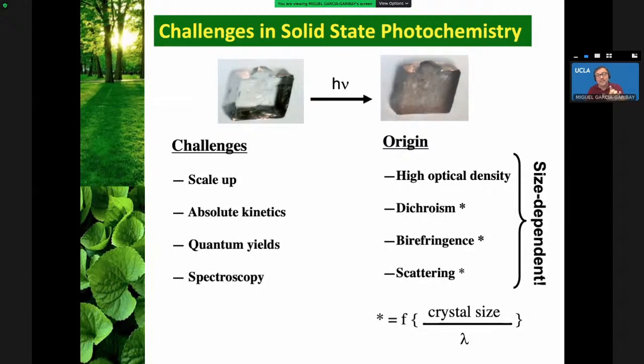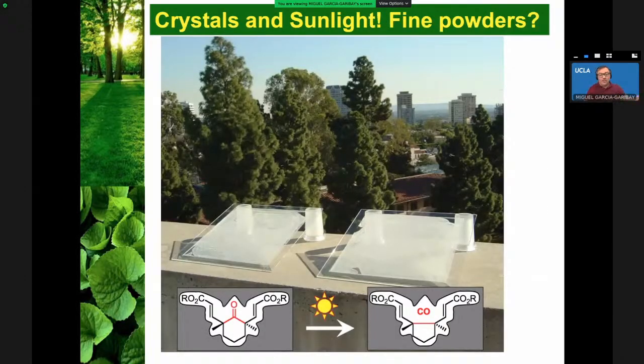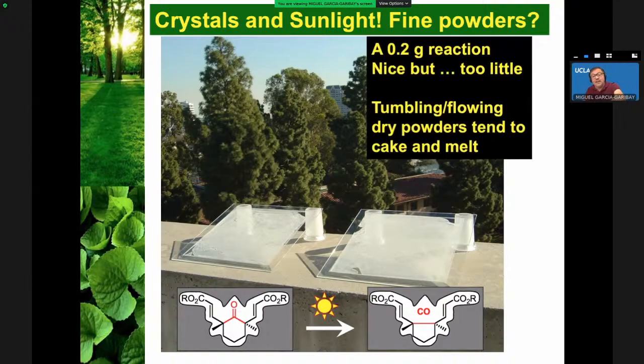That means that the smaller the crystal size, the smaller the problem is. One solution would be to just find powders, right? So we use fine powders, put them on the roof again, and we can do this reaction. It works pretty well, actually. So, we can do 100 milligrams in each of those glass plates. It's good, but it's just not enough, right?